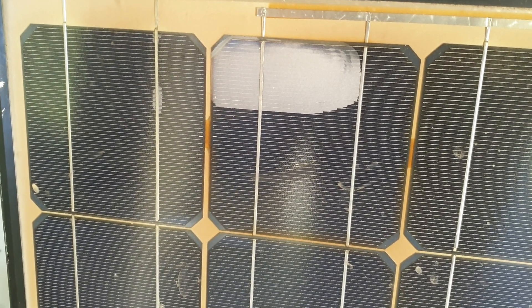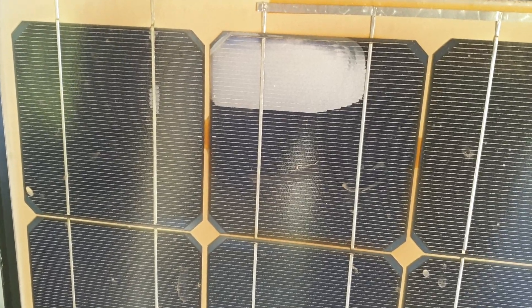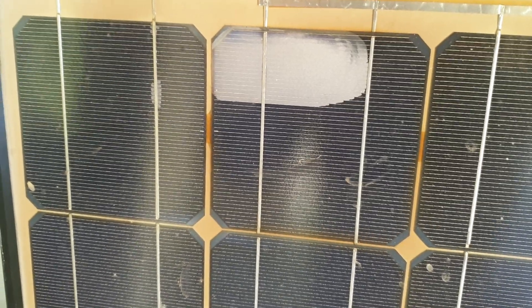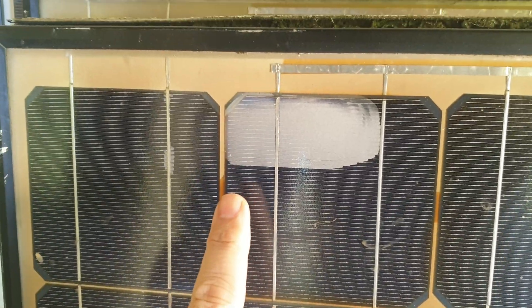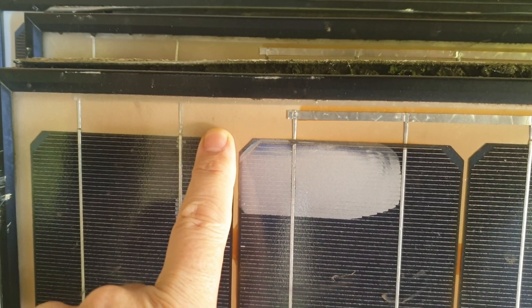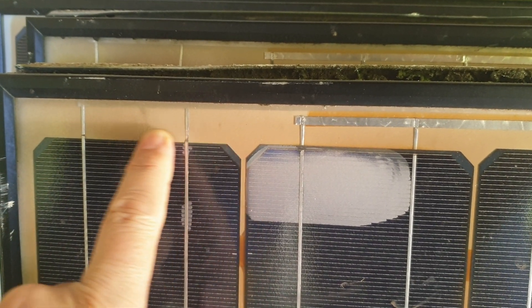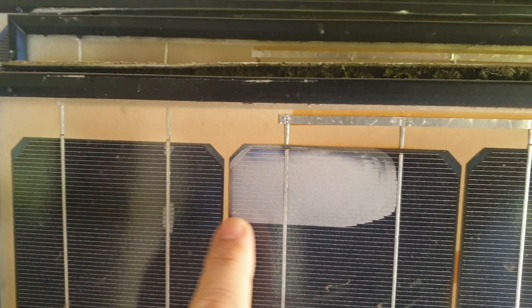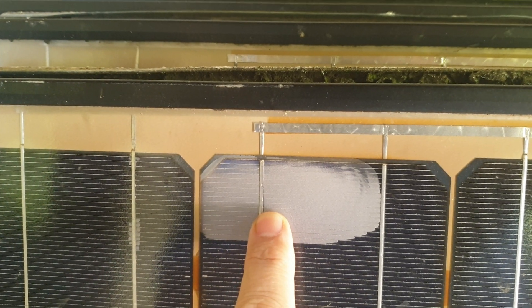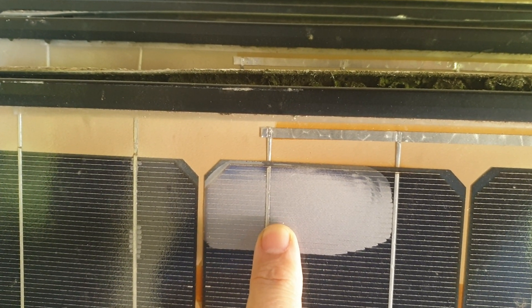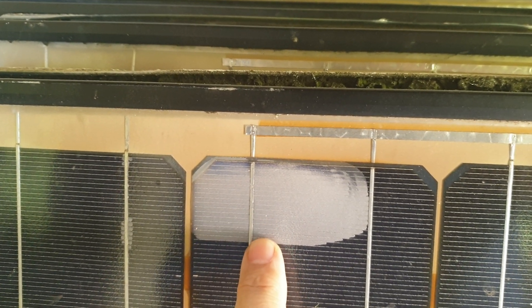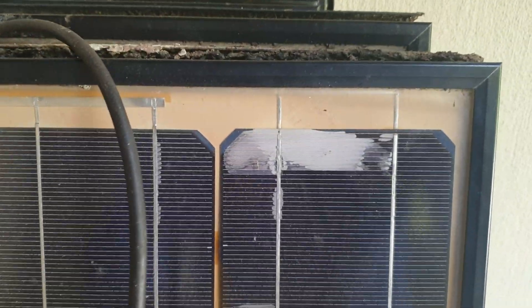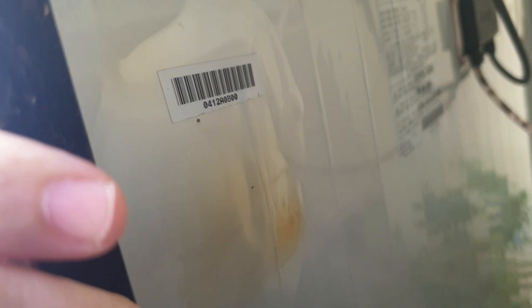These are my Sanyo panels from eight years ago and what you can see is the discoloration of the back sheet here. It's gone all brown and what happens is moisture gets in the back once delamination occurs. I was quite surprised to see delamination all over the place on my panels and that's basically from the back sheet. If you have a look on the back you'll see it bubbling with the corrosion coming through.